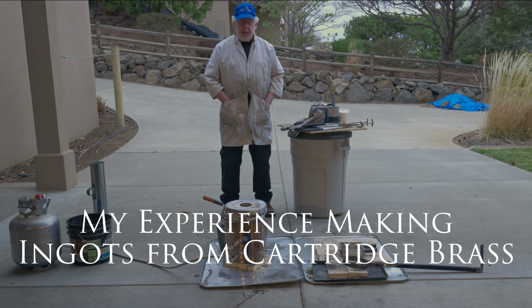I'm showing here that there is white smoke coming out of the furnace, and that means you've reached a critical temperature where zinc is burning off from the brass. I'm turning off the furnace at this point and reaching in with my spoon and lifting off dross that has gone to the top of the pool. We do have a molten pool of brass at this time.